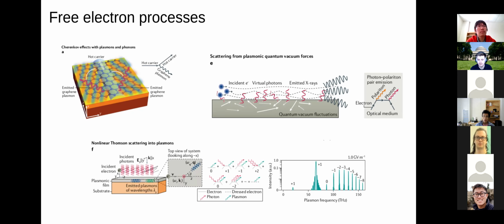One final example with this sort of free electron stuff on this slide is a higher order kind of process where the picture here is that you have a free electron beam going over a plasmonic surface. Then you send in a super strong pulse of light at some lower frequency. And then as a result, you could think semi-classically about the electron wiggling around and acting as a current source. And then plasmons can be emitted either at the incoming frequency or also potentially at several or many harmonics of the frequency that was coming in. So in this sense, the free electron is acting as a nonlinear converter, which under the presence of sufficiently high driving fields will create many harmonics of that driving field in the form of plasmons at different frequencies.